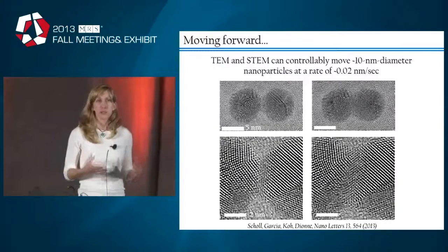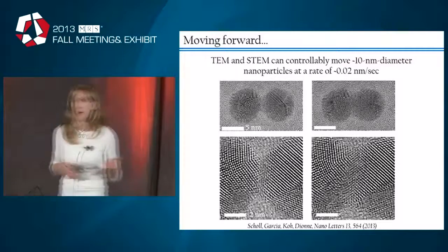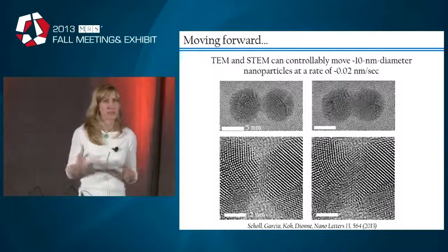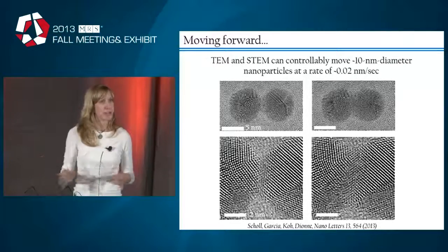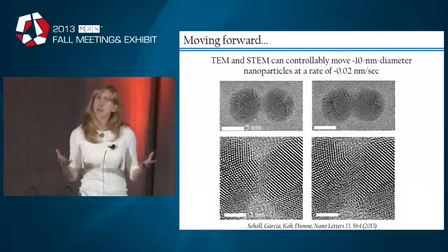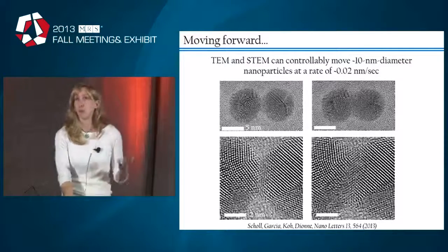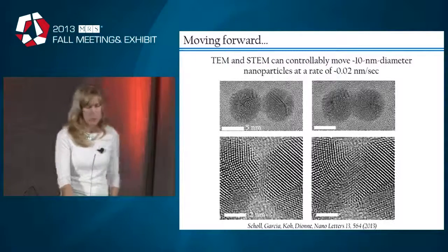So dimers have been used quite a bit in the literature as very sensitive SERS, surface-enhanced Raman platforms. They've also been used as tunable nano antennas, where you can basically tune the receiving and the emissive properties of these optical antennas. And they've also been used as molecular rulers. So there's a pretty significant reason to want to explore their optical properties, particularly as a function of interparticle separation.